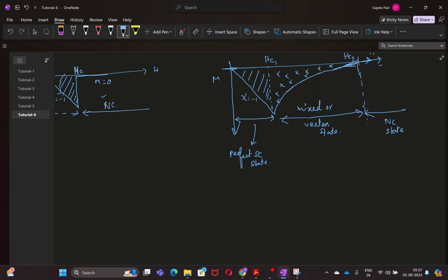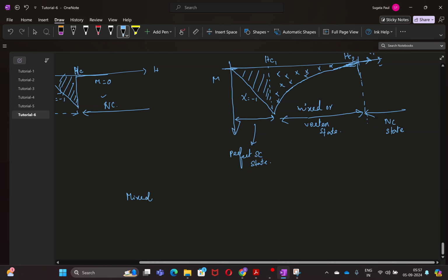So this is also known as the vortex state between Hc1 and Hc2. Above Hc2, the magnetization completely goes to 0, so it becomes a non-magnetic normal conductor state. The mixed state is between Hc1 and Hc2, and it is only seen for type 2 superconductors, sorry. In type 1, this kind of behavior is not seen.